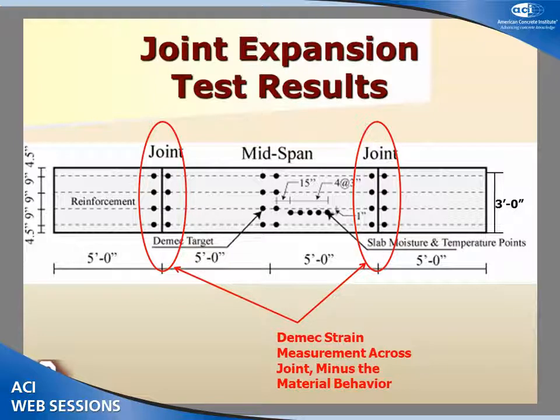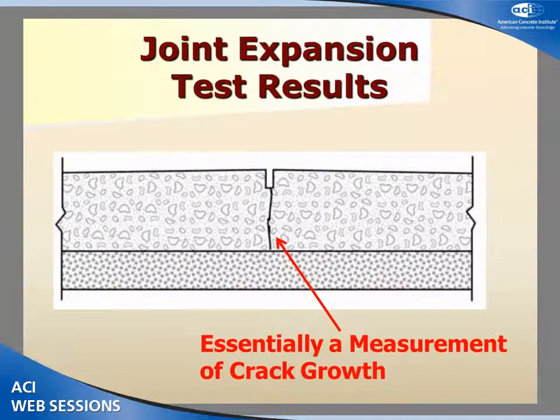Now I'm going to review some of our joint expansion results measured at joint opening from the DEMEC target. I already mentioned that, and this is actually showing the measurements of the crack growth at the joint opening, these results.